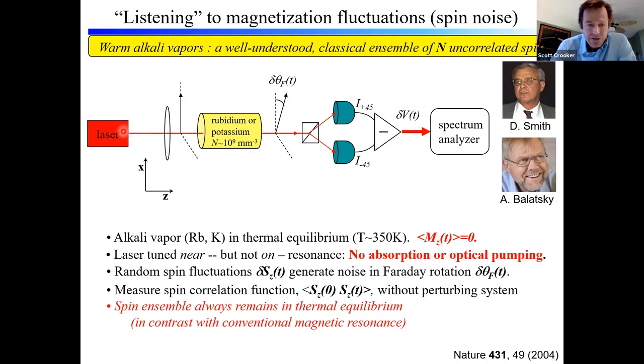And we took a laser and we tuned it near to, but not on, one of these atomic resonances. So there's no absorption of the light. Okay, so no photons were harmed in this measurement. But nonetheless, spin fluctuations in this vapor imparted Faraday rotation fluctuations on the laser that passed through. And we can measure this with tremendous sensitivity, as I'll mention later in the talk. Okay, so I want to emphasize that this spin ensemble always remained in thermal equilibrium throughout these measurements.